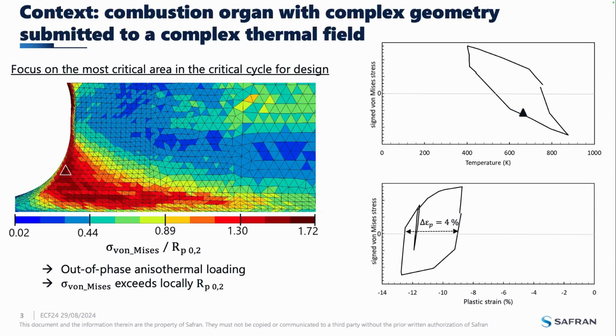And at the critical point, you have there the evolution of von Mises stress as a function of temperature. And as you can see, it is an out-phase anisothermal loading. This loading also induces a plastic strain field with important plasticity, which is supported cycle by cycle with a strain amplitude of 4%.